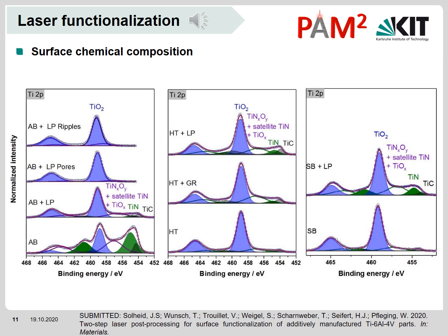For that reason, an analysis of the surface chemical composition was also performed. From this, we could see that certain processes induce mainly the formation of oxides on the surface of the samples, while other processes can induce different reactions between the chemical components. From this analysis, a better relation of surface topography, wettability, and chemical composition was established.